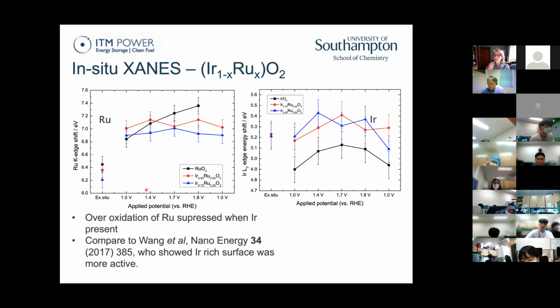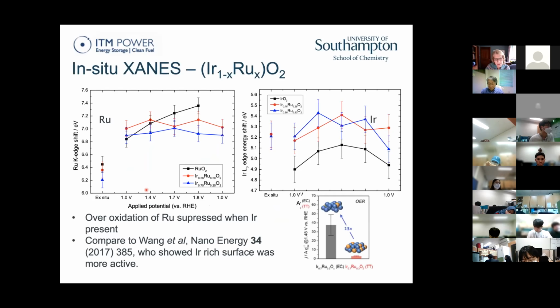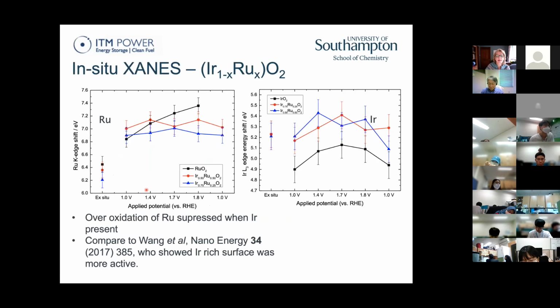And so we then did the experiment under operando conditions. In the case of this cell, because we're going to really be evolving oxygen, we had to flow the electrolyte much more to get the bubbles out of the cell. So there's a slightly different cell design where the electrolyte is purged much more rapidly.